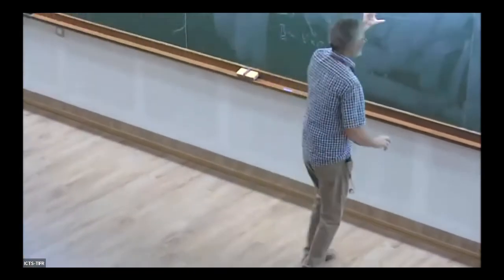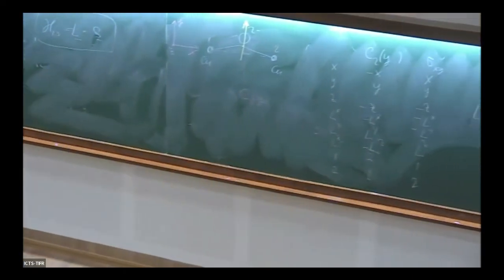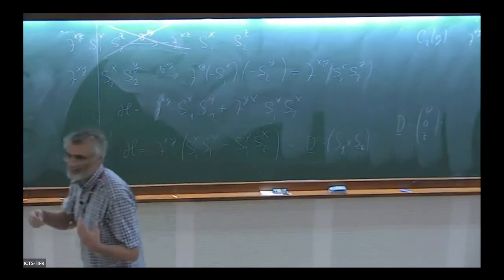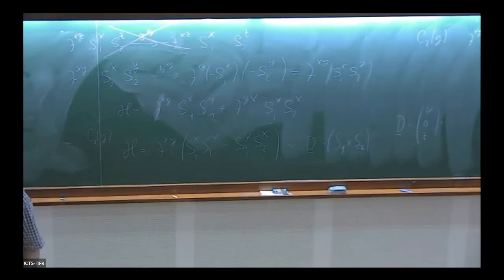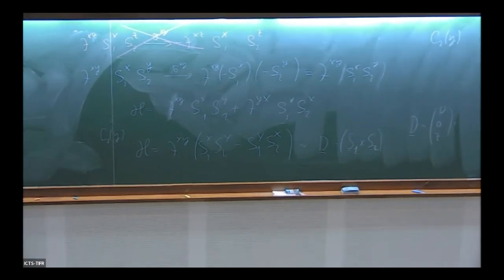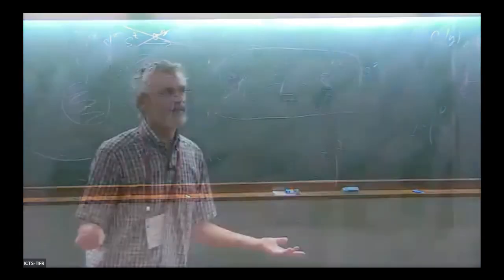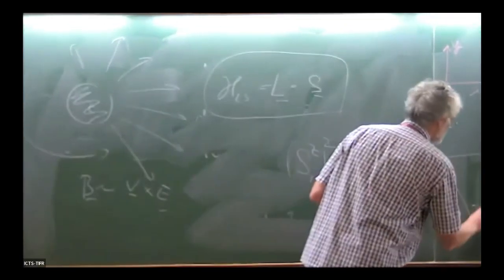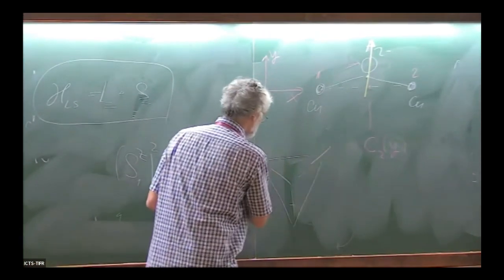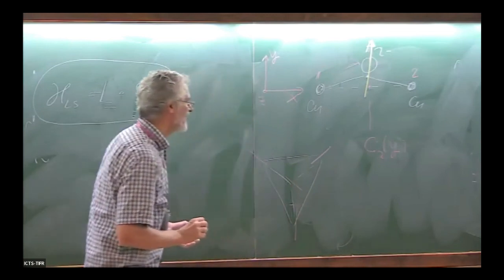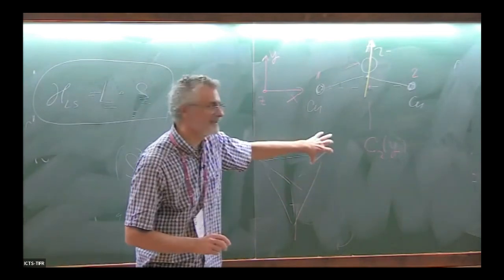Would you briefly comment on single ion anisotropies? We can, why not? Spin-orbit coupling can lead to DM interactions, but even more importantly, if you have a higher spin, like spin 1 or spin 3/2, then terms in the Hamiltonian can appear like S1Z squared. Or if you think about some more complicated systems, like a tetrahedron that is found in the spin ice, then these anisotropies will choose axes that are pointing from the center of the tetrahedron, and these will be special axes.